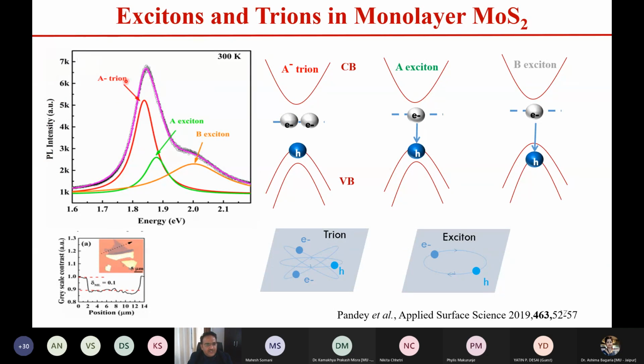And what you see here is that, in general, the understanding for these materials is that there are three different kinds of optical transitions here. So we call them A exciton, B exciton, and A minus trion. So now what are these excitons, okay? Once light is absorbed by the semiconducting or insulating material, the electrons from the valence band go to the conduction band, and there is an electron-hole pair generation. And now because of the Coulombic attraction between these two, they can travel from one atomic site to another atomic site. So they form quasi-particles, okay.